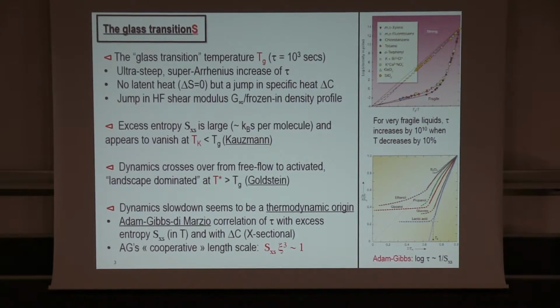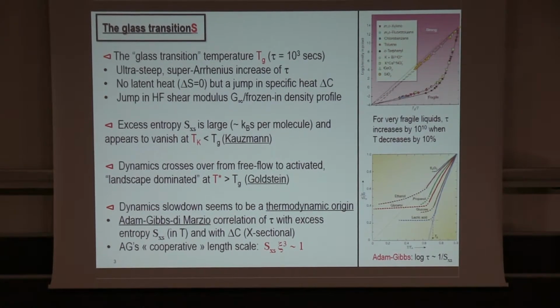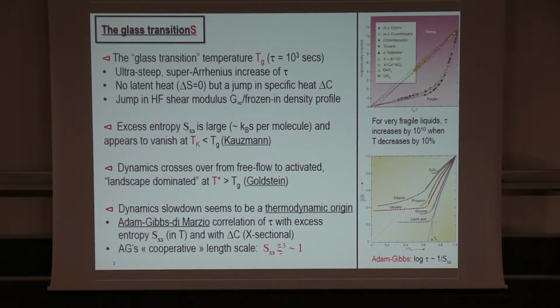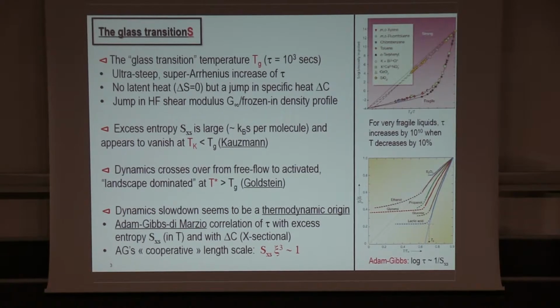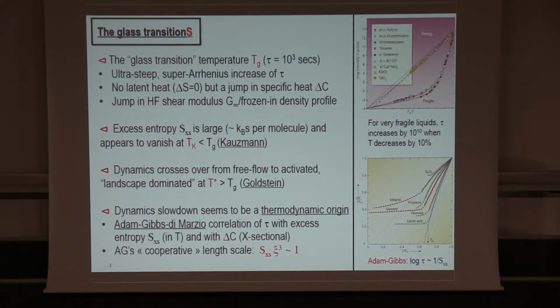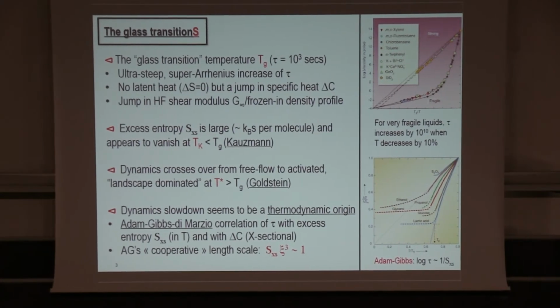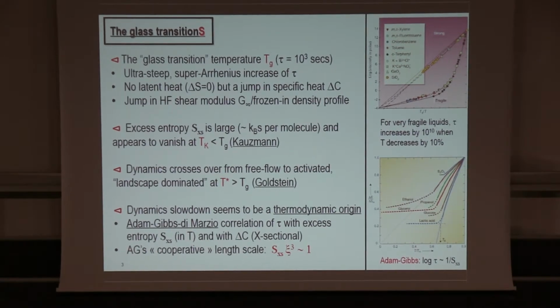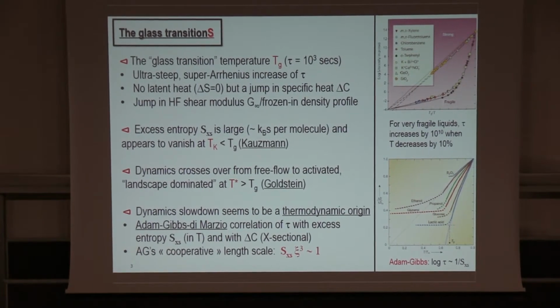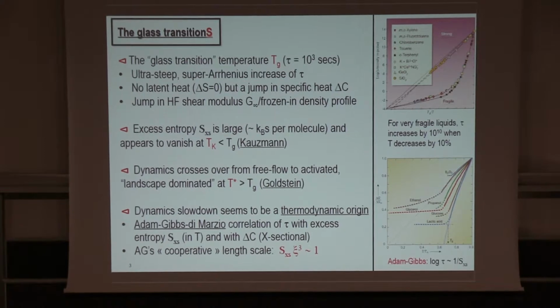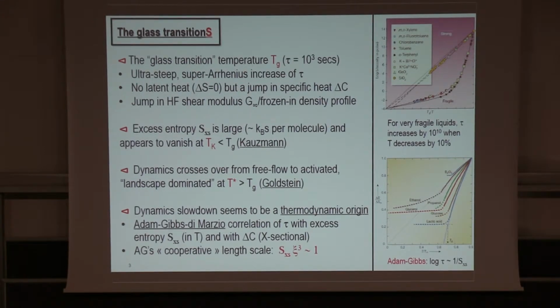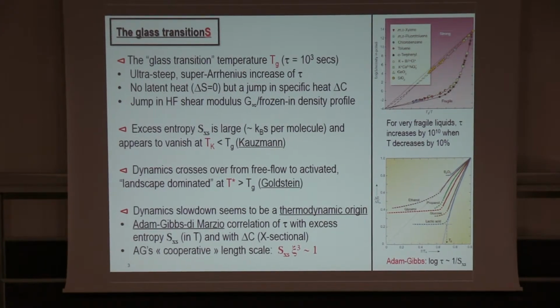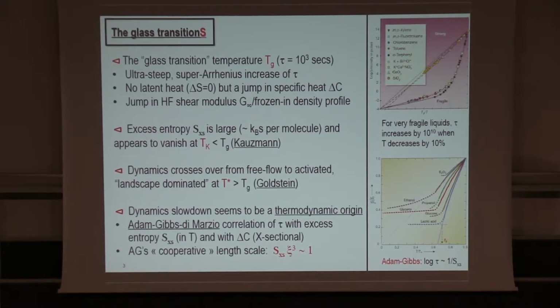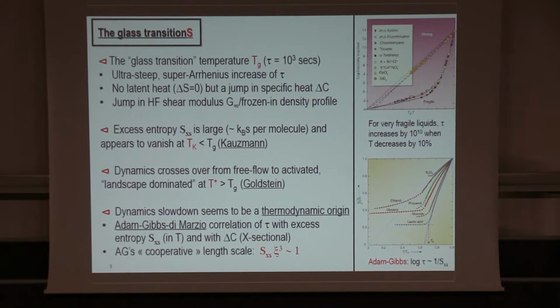And that's the famous plot where the log of relaxation time is plotted against 1/T. And you have to remember that for fragile liquids, it's really a very impressive increase that you see. The relaxation time increases by 10 orders of magnitude when the temperature decreases by only 10%. Around this glass transition, or effective glass transition, there's no latent heat, but a jump in specific heat.